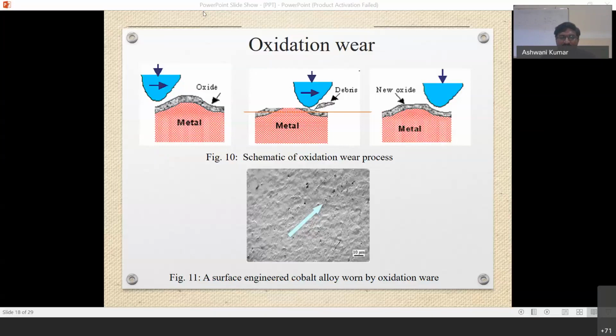The worn surfaces we can see in the next figure, like the surface of a cobalt alloy worn by oxidation wear. The worn surface is smooth and frequently covered with a layer and patches of oxides, which sometimes can be visually seen. For steel, the worn surface becomes dark brown, so we can also characterize it with the help of color, and the morphology of the worn surface can also be characterized.